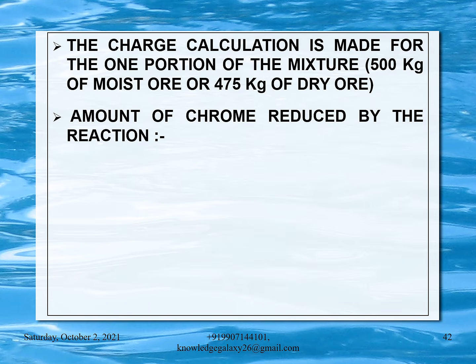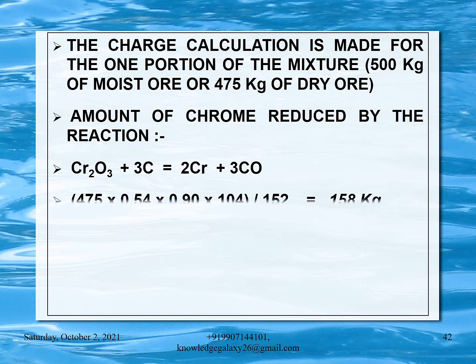Amount of chrome reduced by the reaction Cr2O3 plus 3C is equal to 2Cr plus 3CO. My dear friends, here you have to always keep in mind the atomic weights of different elements, so that you can balance the equations and further calculate the requirements. So here comes 475 into 0.54 into 0.90 into 104 divided by 152, which comes to 158 kg. Here 104 is the Cr2 atomic weight and 152 is the Cr2O3 atomic weight.